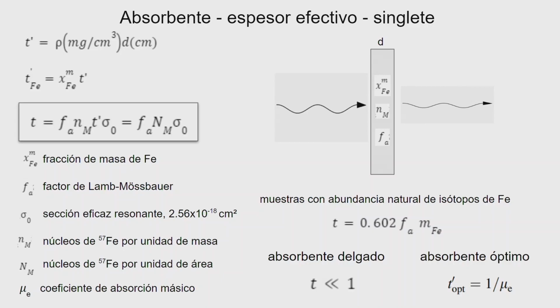So that the effective thickness should be below 1. In principle, at least 1 order of magnitude below 1, in order not to have these effects. Rarely this condition is satisfied, I must say it. But it is very good to keep it as low as possible, okay? It is calculated as a series of quantities which I'm not going to go in detail, but have to do with the amount of nuclei you have in your sample, the cross section for the Mossbauer transition, and so on.